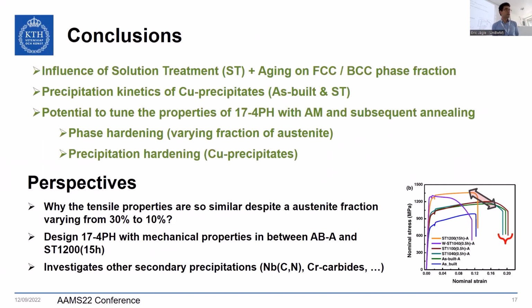So in conclusion, we see the influence of solution treatment plus aging on phase fraction, and also on precipitation of copper precipitates, with a 2-hour aging, which is the peak hardening for this alloy at 480. There is the potential to tune the properties, in terms of hardness, and also maybe later the tensile behavior, through the phase hardening and FCC contents. One perspective of the work would be to understand why this variation from 30 to 10% FCC does not seem to change much the tensile properties of these three alloys, which could also be linked to secondary precipitates like this NbCN that we found only on those alloys and not on this one, for instance, or other factors that we haven't acknowledged yet.